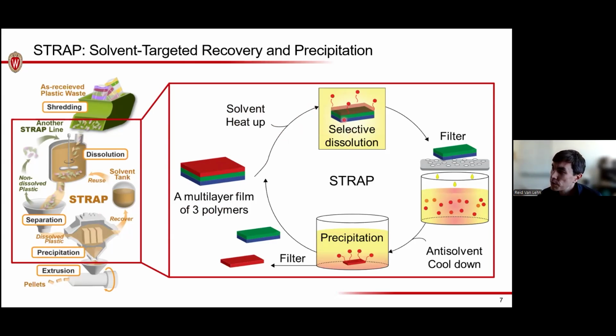So once I've dissolved off this red polymer into my selected solvent, I can filter away the residual green and blue ones. And then I can add in either what's called an anti-solvent, so a solvent that is a bad solvent for the polymer that's been dissolved, to trigger it to precipitate out of solution. Or I can imagine just cooling the entire system down, okay? I get back my red polymer as a solid, and I can do this sequentially. Now that I've got this green and blue one, I can further target a second one of those using a different solvent to separate them.